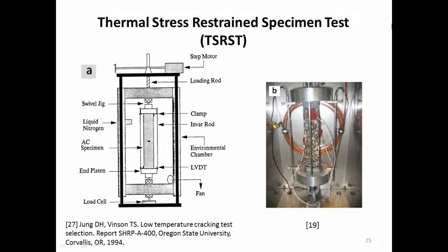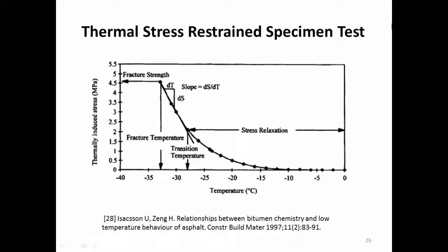Yes, and at one point when your temperature is too low, the specimen will fracture, right? Because if you decrease the temperature, the specimen is supposed to shrink as well, but you hold them there, so it will fracture. And that's the typical curve here.